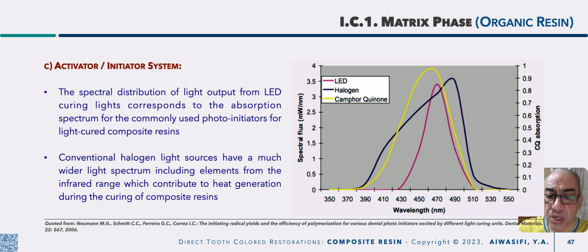As long as you hear that your fan is working, please don't switch off your device, otherwise the latent heat will damage your lamp, and your lamp will not release, time by time, the required wavelengths for curing your composite. And that's why when you use an old device, okay, please increase the time to compensate for the lower output of wavelengths of your device, okay.